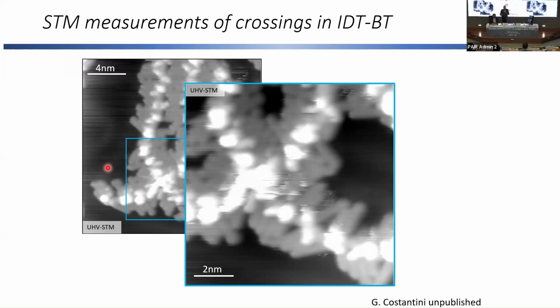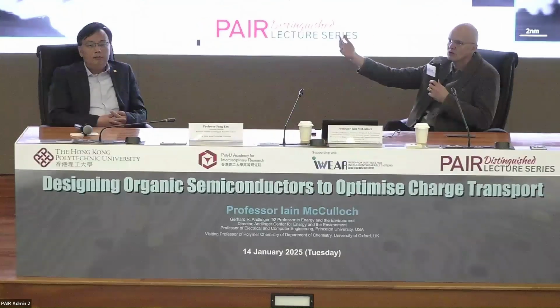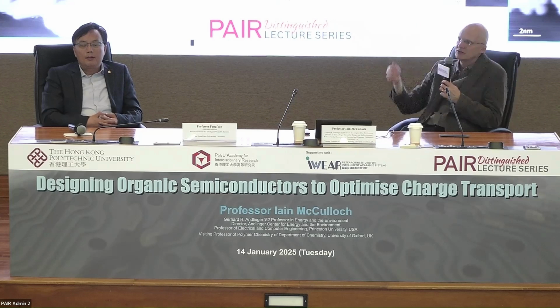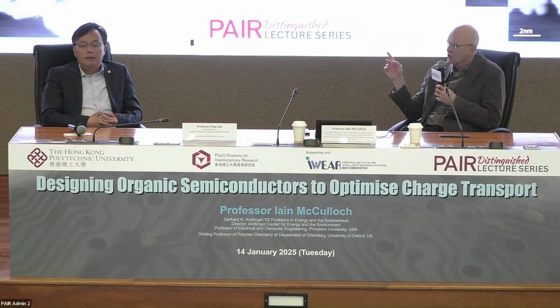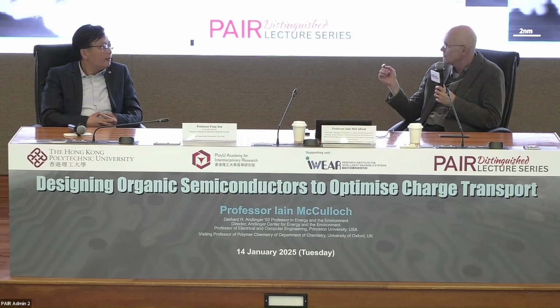One of the potential limitations of this technique is that you do an electrospray on a gold surface. So this is 2D, it's a monolayer. And there are people who say, well, how do you know that this image projects all the way into the bulk and it's not just a surface effect that's templated by the gold surface? But in every sample we've looked at, if we see any type of order and we physically measure on the image the distance between polymer backbones and then compare that to the 3D bulk X-ray to see what that reflection corresponds to, they match perfectly. So I'm very confident that the type of assembly that you see on the surface of gold is consistent with the 3D bulk.